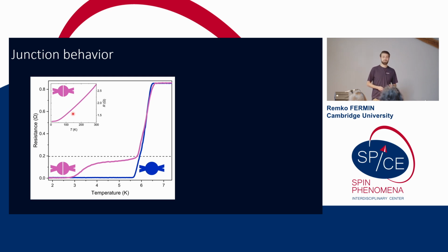And what we see is that there's only a single superconducting transition, which is basically the superconductor shorting out the bottom ferromagnet. But once we structure the trench along the diagonal of the device, we see not only an initial transition owing to the contacts, but also a second transition corresponding to the weak link of the device.